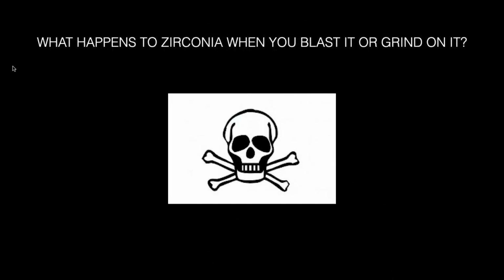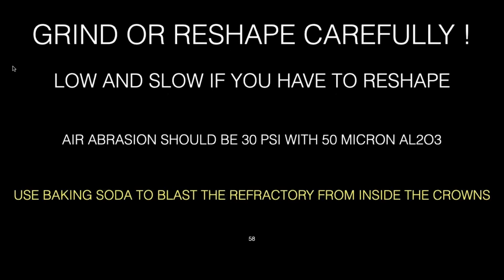So what happens to zirconia if you blast it too hard or grind on it? We know that if you put too much pressure on the zirconia, it'll actually push back. And then you can air abrade, but it should be about 30 psi with 50 micron aluminum oxide. What I've done is, since you have to blast out sometimes the crowns when you layer them, refractory material to hold the bridges in place, I blasted out the VITA one because it sticks. I don't like that one so much, but a lot of them are like that. They have like a little tacky thing which holds it up nicely, but to take it out is more of a bear. And what I do is I used one of the tanks in the blaster with baking soda. Now, any of those things absorb moisture. So what I did,